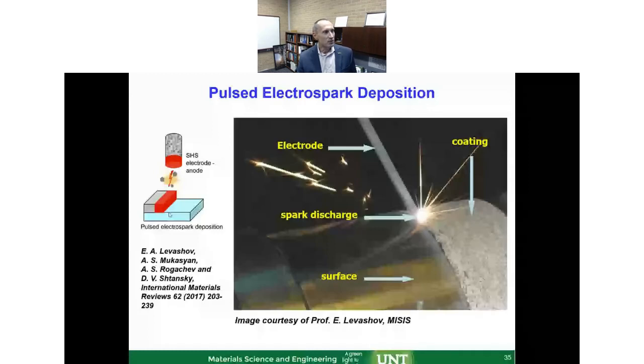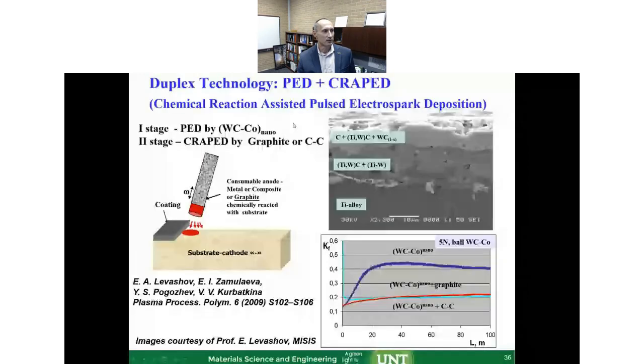With that, you can now move to make this type of adaptive material, where you also engineer a very good supporting base. This is an example of a technology called chemical reaction-assisted pulsed electrospark deposition. Using those different electrodes, now talking about strengthening titanium alloy, you can drive the formation of titanium tungsten carbide, with some ductility provided by titanium tungsten, so you have a very well metallurgically bonded and hard supporting base. And you can finish with a material which contains carbon. The carbon is there for lubrication, and the effect you can see for yourself.